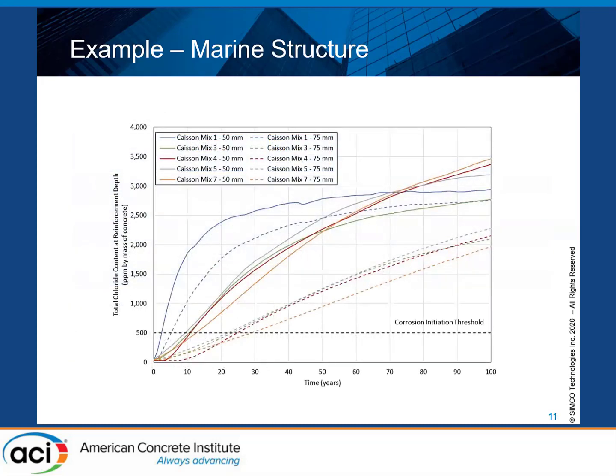The results that we get with the STADIUM modeling here, you have the chlorides expressed at reinforcement depth, as a function of time. So the solid lines are at 50 millimeters from the surface. The dashed lines are at 75 millimeters from the surface. And you can see that based on the modeling that we did, none of these mixes get us to a corrosion initiation time of 50 years, and even less, 75 years. So the most that we can get is 30 years.